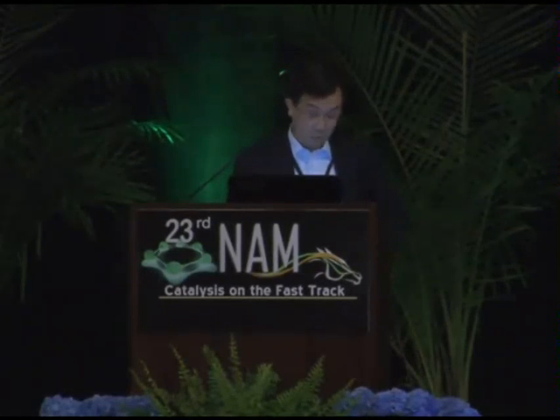In the enzymatic reaction, in the retention type reaction mechanism, you need the carboxylic acid and conjugated carboxylate on the enzyme surface. This base carboxylate attacks the C1 position of the sugar, and then water attacks again to give the beta anomer of the sugar. This is a retention mechanism. And in the inversion mechanism, first the carboxylate attacks water, and then the OH attacks the C1 position to form the alpha anomer as a product. This is the inversion mechanism. But you need the coexistence of a carboxylic acid and a carboxylate in the enzymatic process. So you need careful control of the pH of the reaction solution by using a buffer.